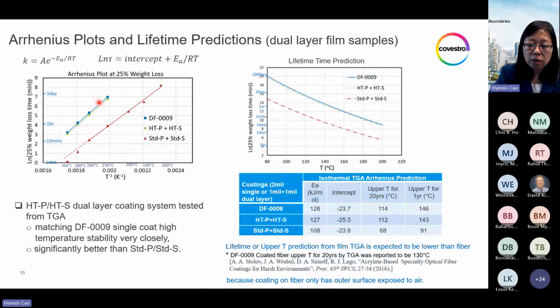Now, this test is with the dual layer film sample where the drawdown was made with 1 ml of a primary plus 1 ml of a secondary on the top. And this is to simulate the dual layer performance on fiber. It shows that the HTP and HTS weight loss is closely matching a single coat DF-0009, which significantly shifted higher than the standard primary and secondary.